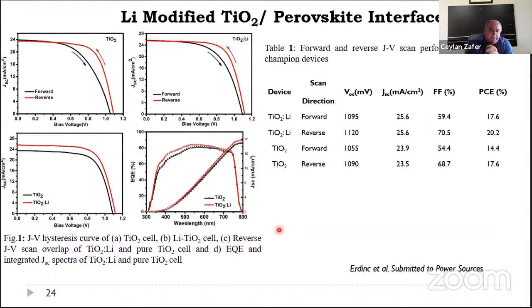Another performance improvement strategy for perovskite solar cells known in the literature is that titanium oxide, which is an n-type transport layer within the device, should be doped with lithium ions, which removes the defects of the titanium oxide located between the Fermi energy level and the conduction band. And these defects make non-radiative recombination centers and increase the recombination rate of the device. Doping lithium into the titanium oxide improves the device efficiency as seen here. And now we have an optimized n-type material, p-type material, and perovskite material for improved efficiency perovskite devices. And these are known in the literature.